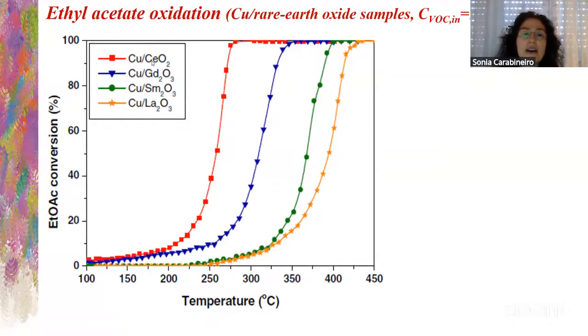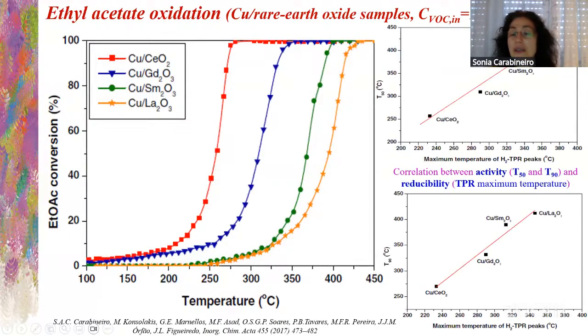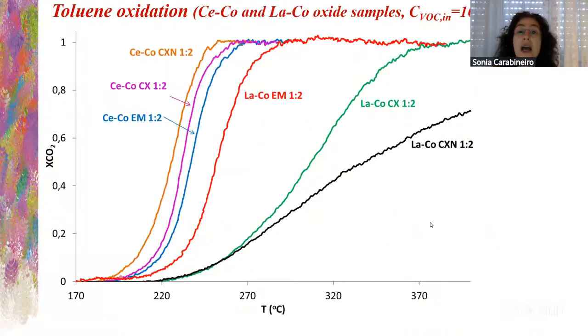Okay, we have here again ethyl acetate oxidation, but now it's copper on the rare earth oxide samples. So here on cerium oxide, gadolinium, samarium, and lanthanum oxide. So we see here that cerium oxide was the best result. Again, a correlation both between the T50 and T90, so the temperature of 50% and 90% conversion, and the reducibility. So you see here this relationship that we found. Also for the oxidation of toluene, for cerium cobalt and lanthanum cobalt oxide samples.